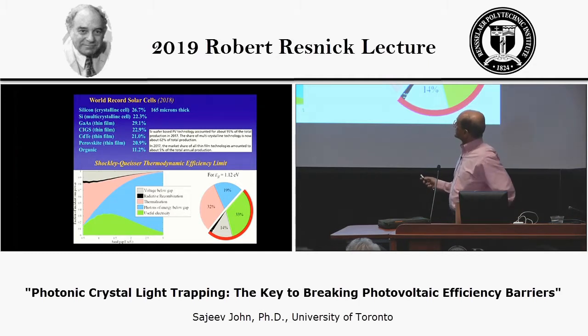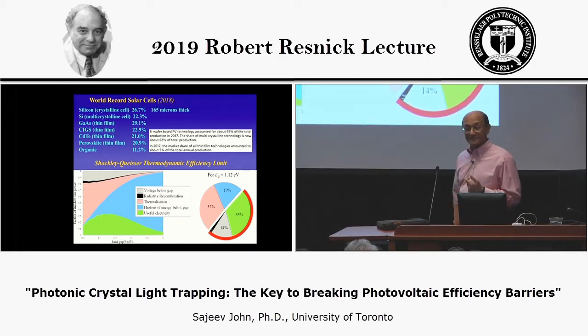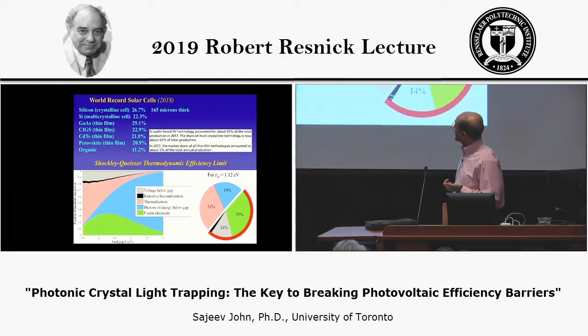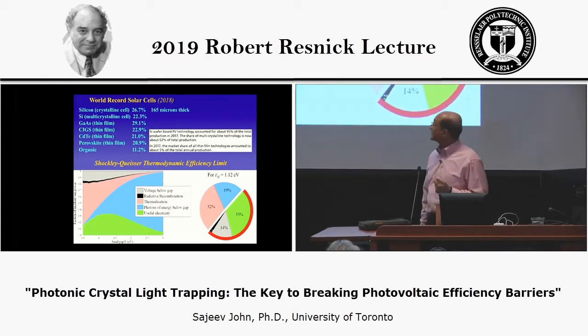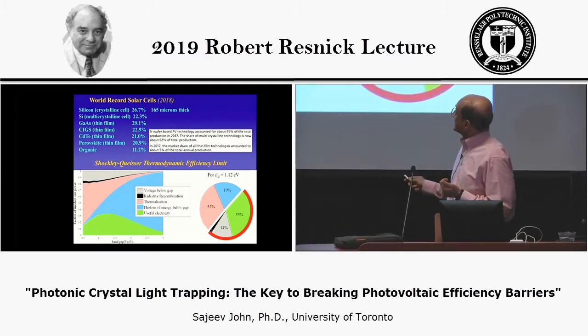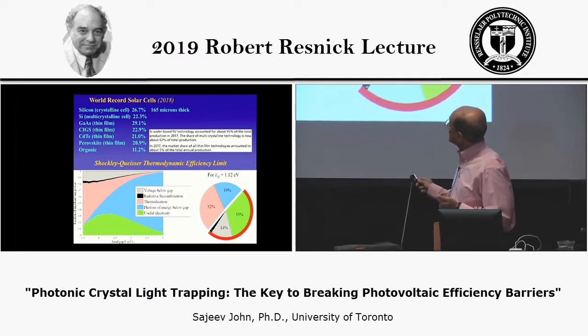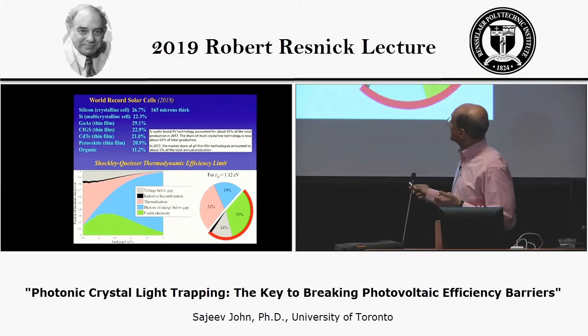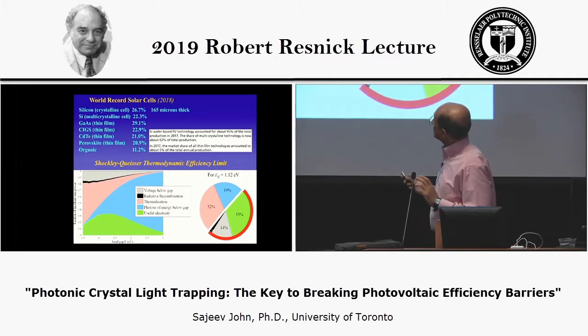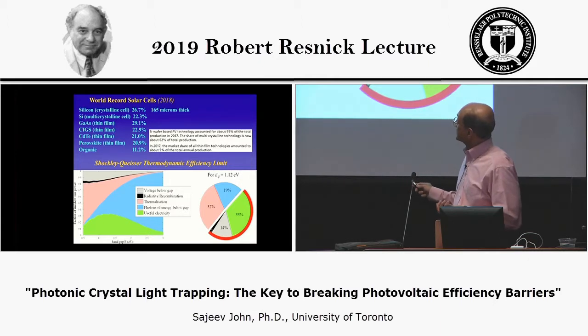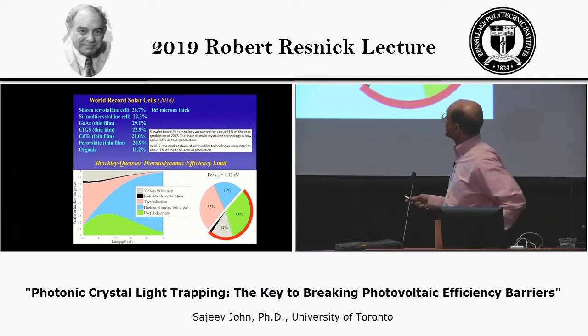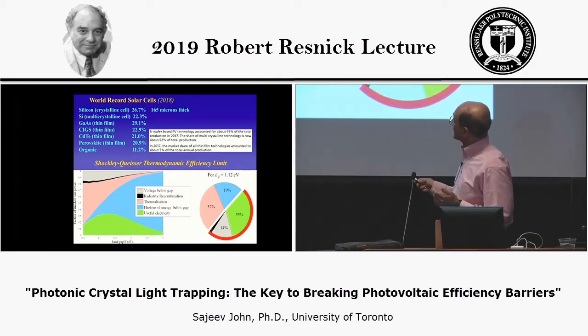Additionally, there are a number of thin film structures, starting with this gallium arsenide structure, which has demonstrated an efficiency of about 29%. This is a direct band gap semiconductor, so it's much more straightforward to absorb the carriers, and the thickness of that was about 3 microns. Other thin film structures include copper indium gallium diselenide, 22.9%, cadmium telluride, which is also used in certain solar farms with about 10 micron thickness, with similar efficiency. And then as you go down, there's been a lot of excitement surrounding perovskite materials, which can be created from a solution-based starting point, so very inexpensive to produce. And finally, organic solar cells, which have much lower efficiency.